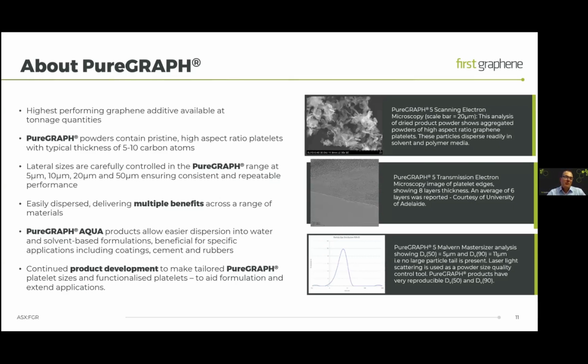The other parameter which we can carefully control is the lateral size. And the reason we do this is, again, to protect our formulating downstream customers. It's really important that there's no drift in the oversized materials in these raw additives. So the image you see at the bottom right is a particle size distribution of one of our products. And you can see on the high side, it has a very well controlled cutoff. So there's no oversized materials in here, which give formulators, plastic compounders, all kinds of issues if they're present. So this is something that our customers really like about the Puregraph products.